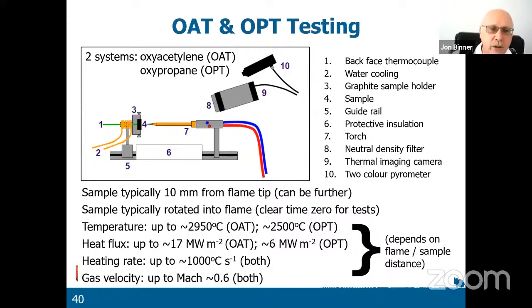The sample is on the left-hand side of that figure. It's number 4. Then you've got the torch itself, and we can measure the temperature using both a thermal imaging camera and a two-color pyrometer. And at the bottom there, you can see some of the conditions. The oxyacetylene, 2,950 is the highest temperature we've measured. With the oxypropane, about 2,500.